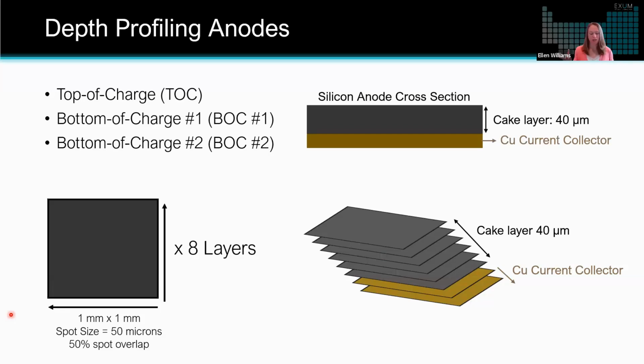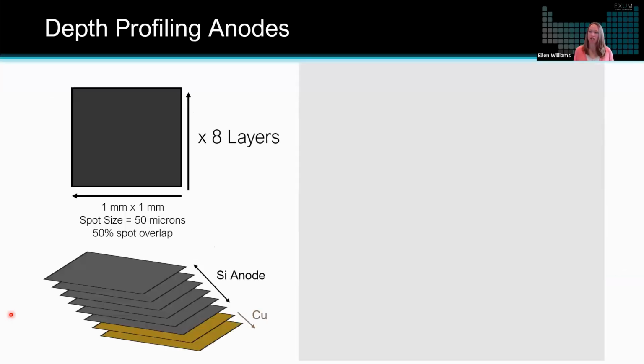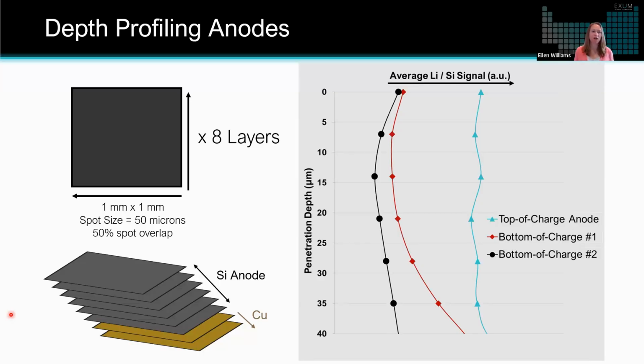So what we determined by doing this analysis is essentially we got 6 layers through the silicon, and then by the 7th and 8th layer, we were seeing that copper signal, which showed us that we had penetrated into the copper current collector. So now what we're going to look at is how is that lithium distributed across these different layers. And essentially, we just integrated the lithium, normalized it to the silicon, and compared that across the 3 samples for those different layers penetrating through the depth.